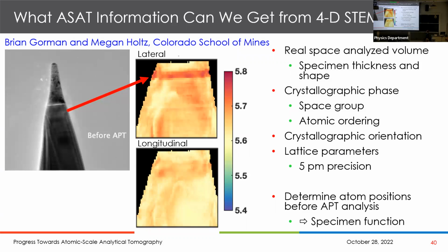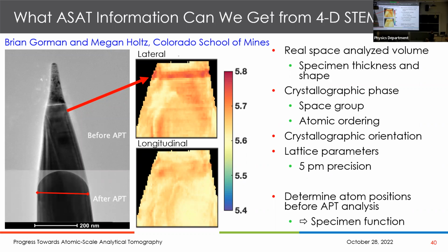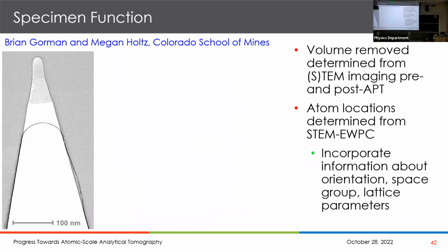I don't want to spend too much time, but this is similar work from Brian and Megan on an oxide, well, it's in germanium. I think there's an oxide layer here. I realized I didn't spend a lot of time on preparing this part. It's their work, but what you're really getting, you can see here, is the atom position displacements from ideal in the lateral and in the longitudinal direction. And what's especially important is he's focused on this region right here, right below the oxide layer. This specimen went into the TEM before it went into the atom probe. And then after the atom probe, all of that material had been field evaporated. You can see the nominally spherical surface after evaporation.